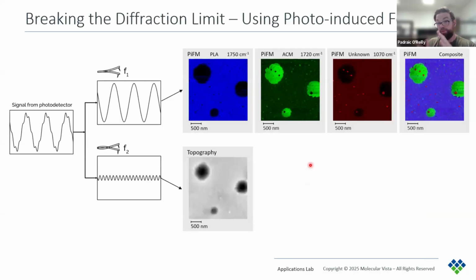So again, we're using two eigenmodes of the cantilever, so we can simultaneously collect topography and chemical information. In this example here, the IR laser is set to one wave number. The tip is scanned across the surface. Then any region that has an increase in absorption at that wave number will appear brighter in the map, meaning we can highlight the locations of specific chemical species.